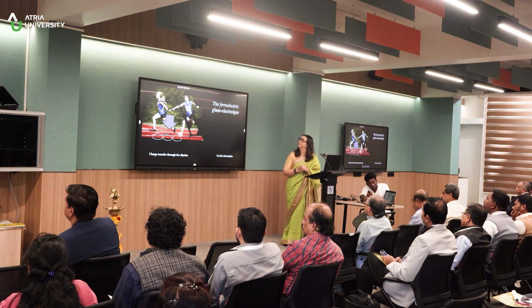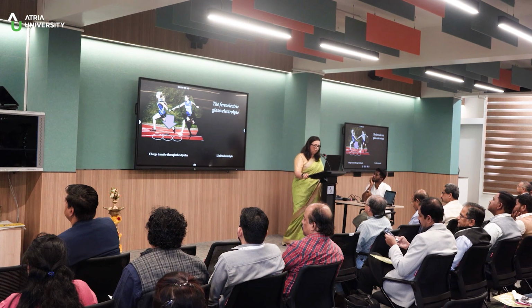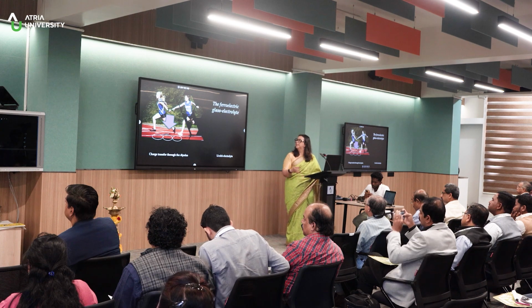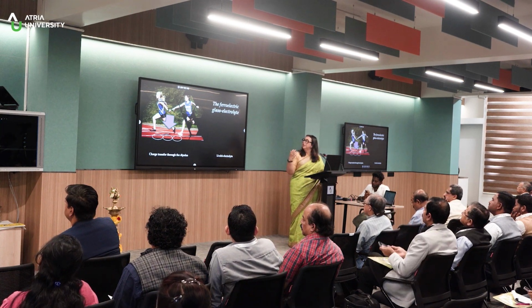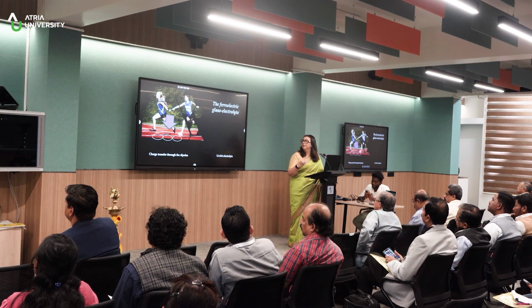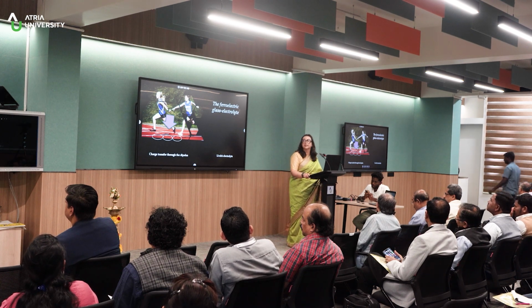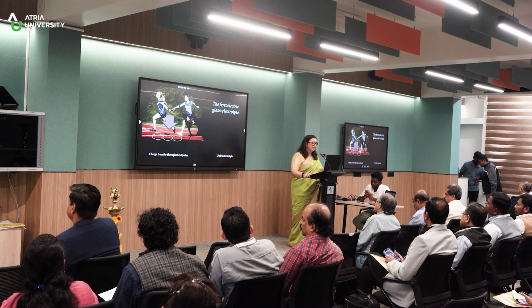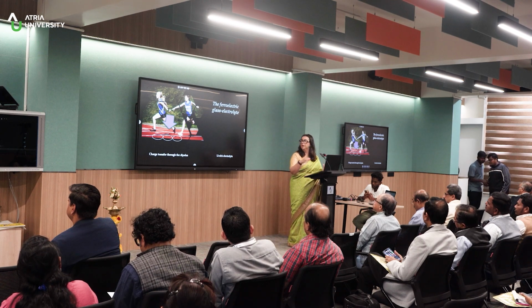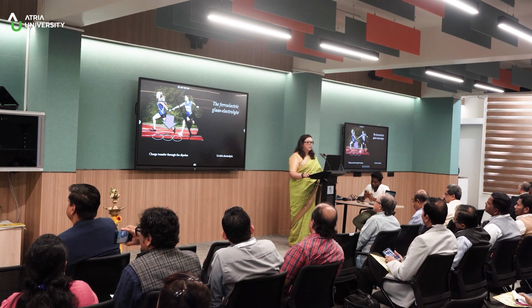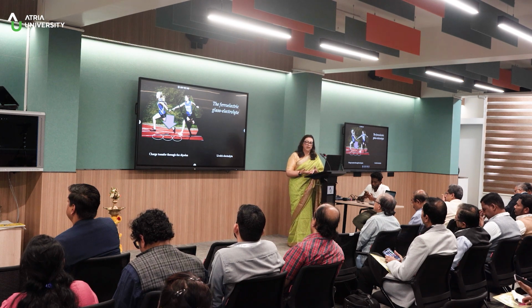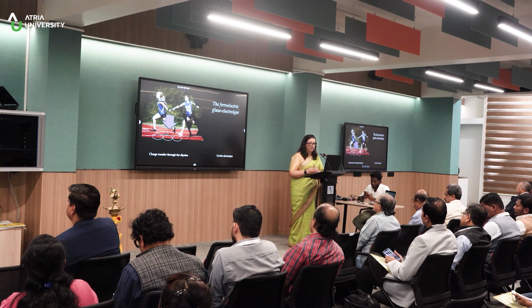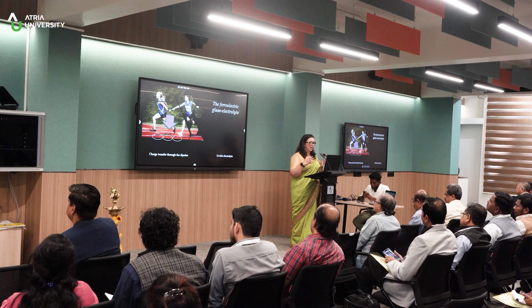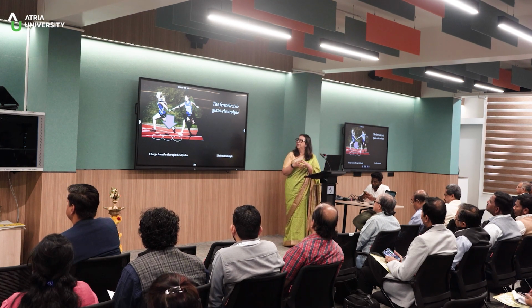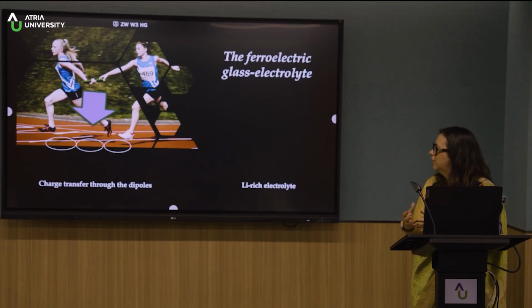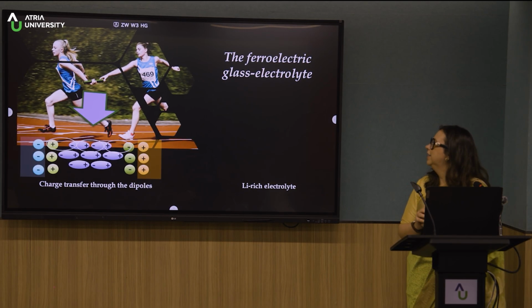So what did we come up with? What was our latest work? Using these materials that will bring something extra to the game without us having to do anything about it. So, ferroelectric material, by definition, is a material that will polarize instantaneously, at a certain temperature or below a certain temperature, the Curie temperature, without having to apply any work. So this is a property of certain materials. And if we find electrolytes that have this property, then we can have energy stored spontaneously without doing anything. We don't need to charge the cell for that to happen, because they will polarize instantaneously.